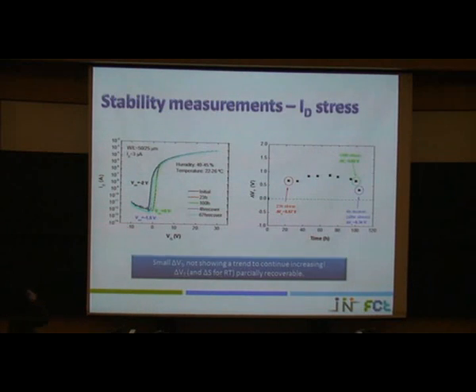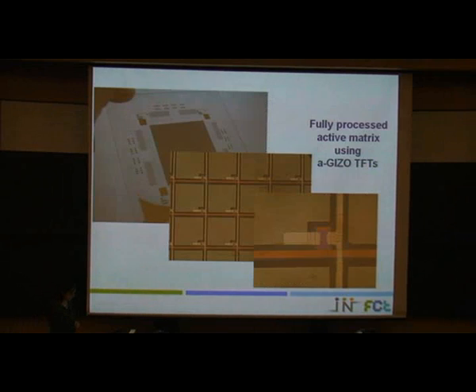And we perform also stability measurements, because this is critical for the display industry. The devices should work. First of all, they should work. Secondly, they should be stable. We perform some stress analysis, and even, for example, after 100 hours, the shift associated with the threshold voltage was around 0.36 volts, which is very low. So this is much better than, for example, amorphous silicon.